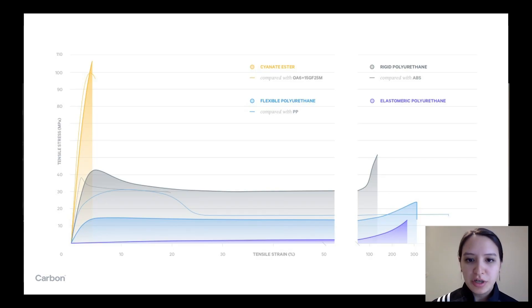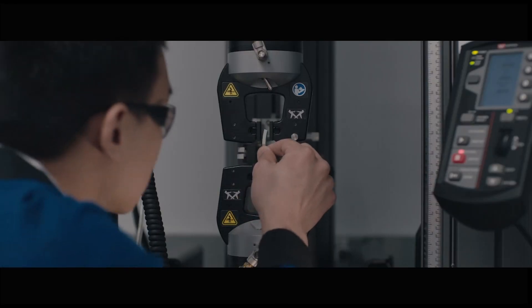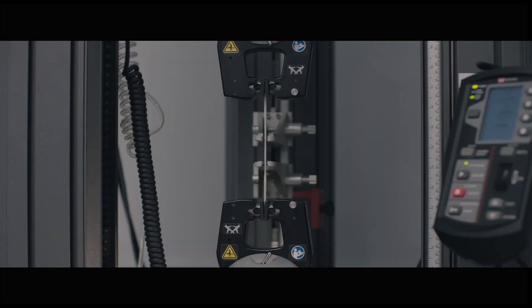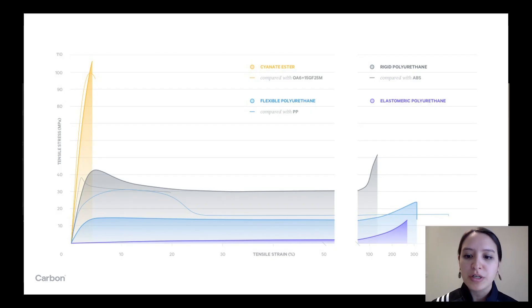Carbon offers an incredibly wide range of 3D printing materials with a really wide range of behaviors in terms of Young's modulus. Starting from the lowest, the elastomeric polyurethane has a really low curve near zero stress and strain — almost no slope — so it has a very low modulus, in the range of 1 to 10 megapascals. Materials from there increase in rigidity; you might be able to bend them a little bit, but they wouldn't be as stretchy or rubbery as an elastomer. Correspondingly, that modulus is increasing — that slope between the tensile strain and tensile stress is increasing at those small reversible deformations.